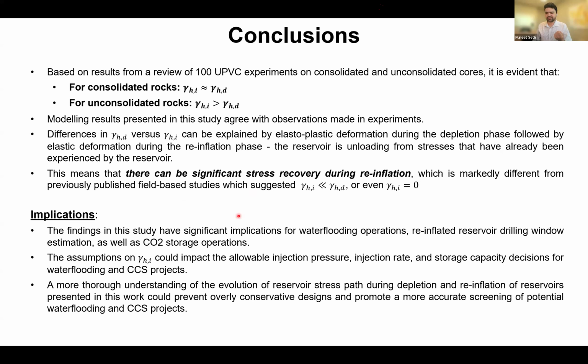So what are the implications? This is very interesting, right? Why this is important is that now we know you should expect stress recovery during injection or re-inflation. What this means is that we can avoid some of those overly conservative designs during planning of an injection project, be it water flooding or CO2 injection. Since we know that there will be some stress recovery, you can maybe inject more, or you can have less conservative injection rates and maximum injection pressure, because you know that the stress is going to be recovered.